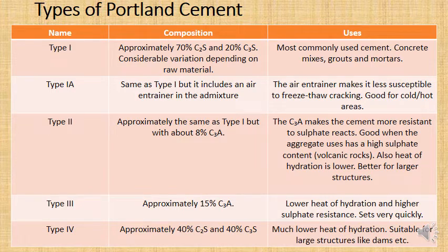But basically, if I can just explain it briefly here, if you're building a really large body of concrete, and I'm talking something like a big dam, and you pour concrete into your mold to build this dam, that concrete is going to have Portland cement reacting with water, and as it's drying and as it's reacting, it's going to let off heat. Now, the concrete on the surface, the heat can escape. It can go into the atmosphere.